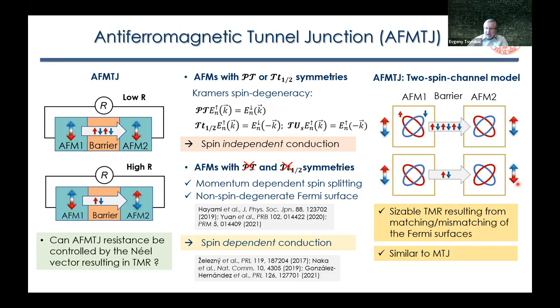On the other hand, if we now flip all the magnetic moments, that means we switch the Néel vector orientation, we have a mismatch between the Fermi surfaces because spin assignment to these Fermi surfaces is reversed. And we should expect that conductance in this case can be strongly suppressed. So this concept, as you can see, is very similar to the idea of a magnetic tunnel junction, because we again are discussing matching or mismatching of the Fermi surfaces. The only difference is that we don't have net magnetization. We don't have net spin polarization.